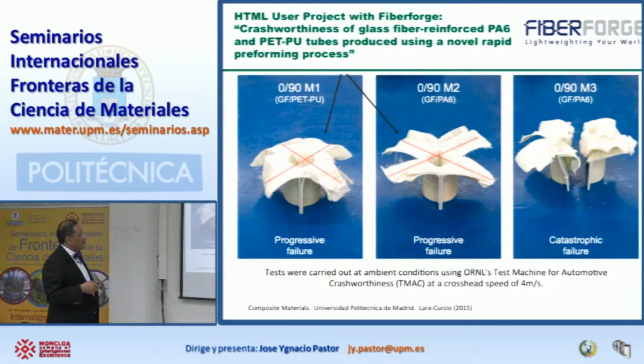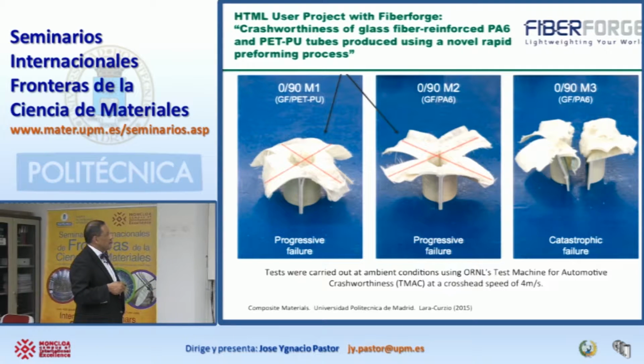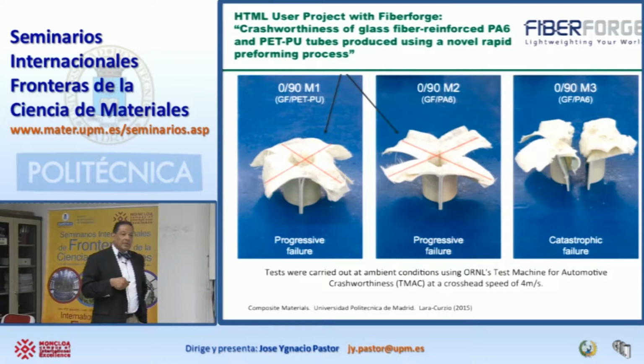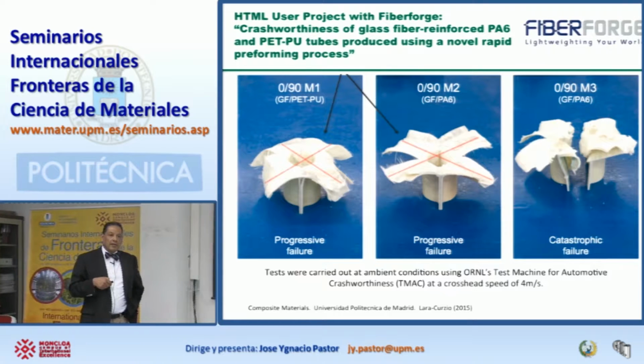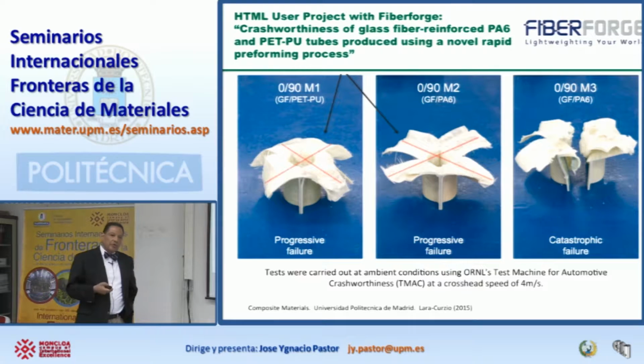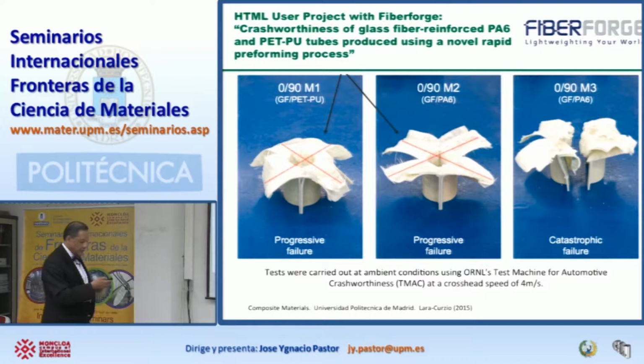So when you compare the energy dissipated by these systems with metals, these materials have twice the amount of energy absorbing capacity compared to steel. And they have half the weight, if not a smaller fraction. And this is exactly what you want in an automotive structure. You have something that will be light, something that's going to be strong, something that's going to be stiff because you don't want your car to be deforming when you are driving at 60 miles an hour. But you also want something that will absorb a lot of energy if you have a type of accident.